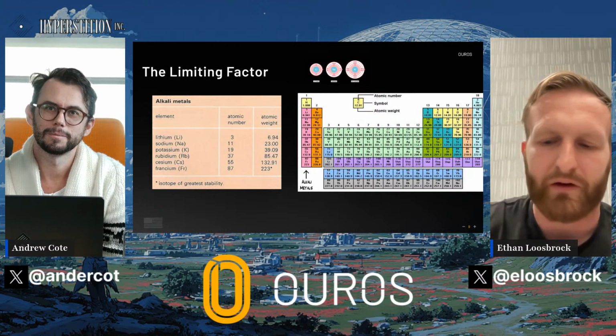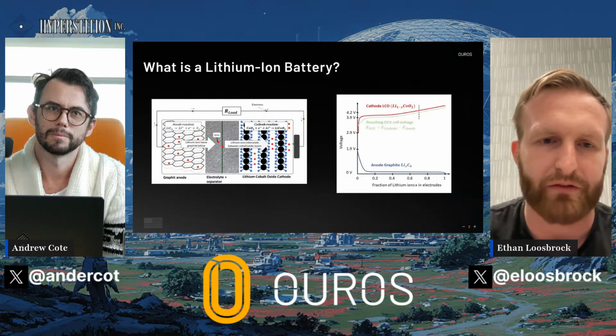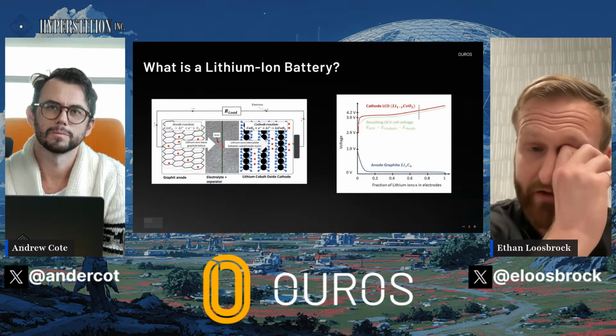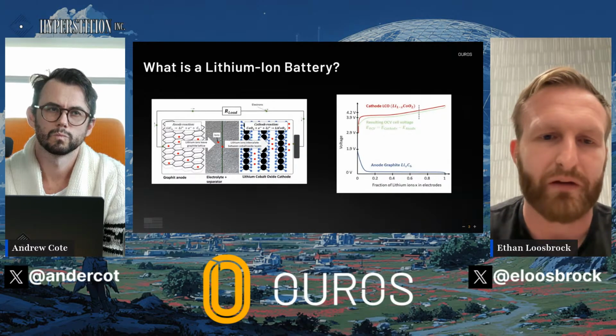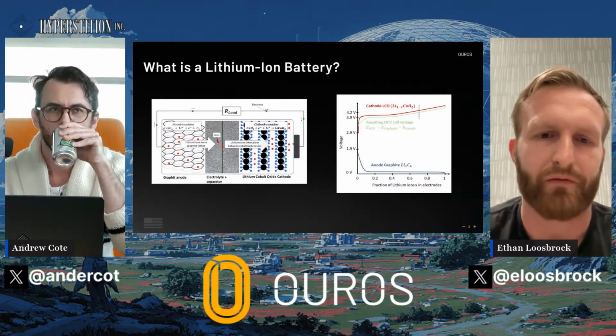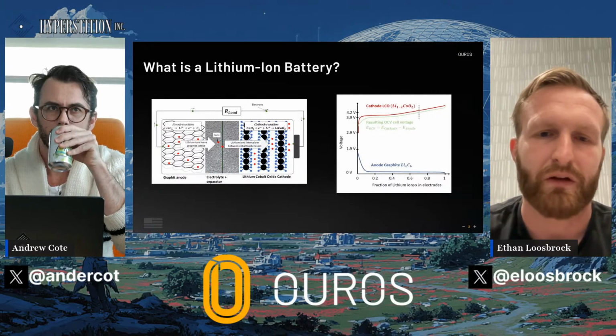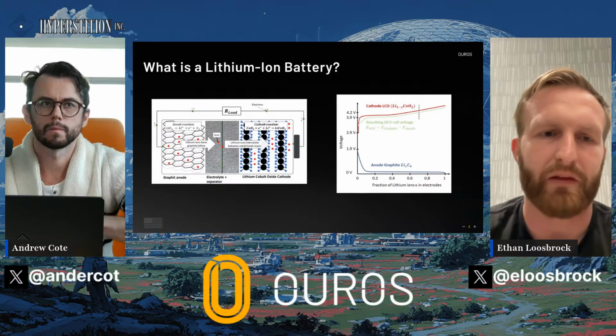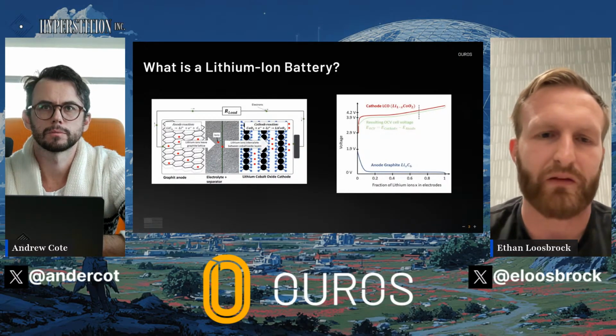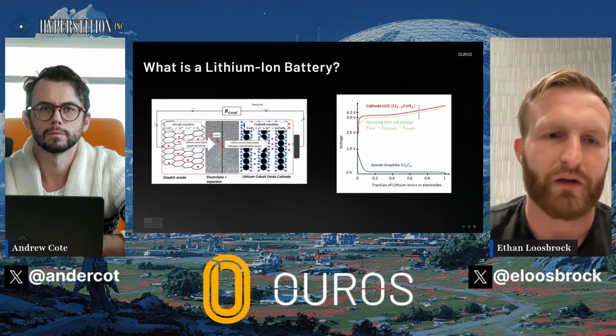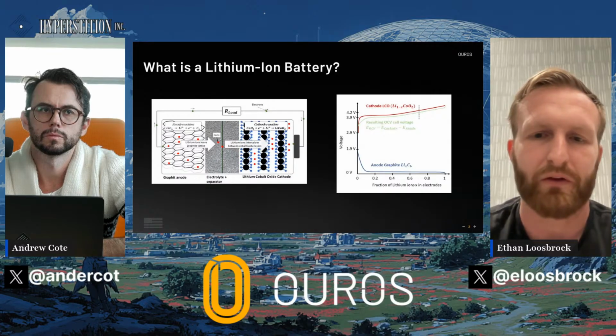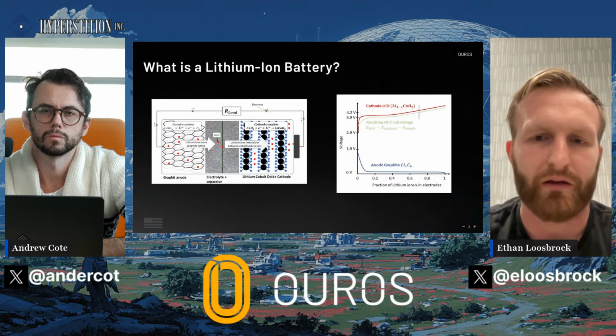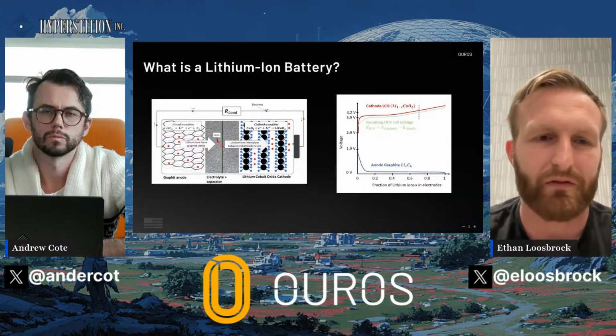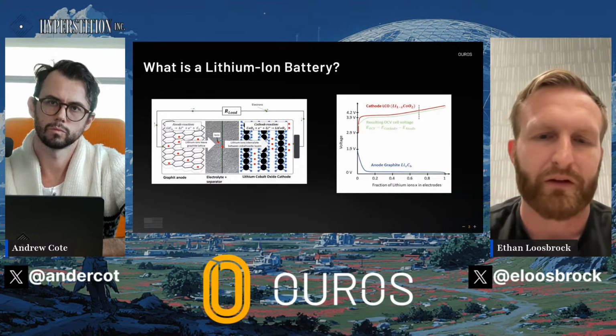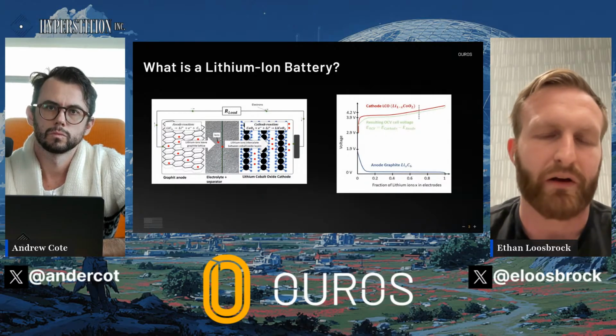So if we're looking at these reactions here, these are the reactions that actually are doing work in the battery. But because you have so many components, I mentioned the binder and the carbon on each electrode, so you're already at six components. And then in the electrolyte, which is the liquid in between the electrodes that serves as a medium for the lithium to move back and forth, you have a lithium salt, sometimes 2, and then 2 or 3 solvents, and then anywhere from 3 to 7 additives. So now you're up to close to 20 different components that are interacting with each other.